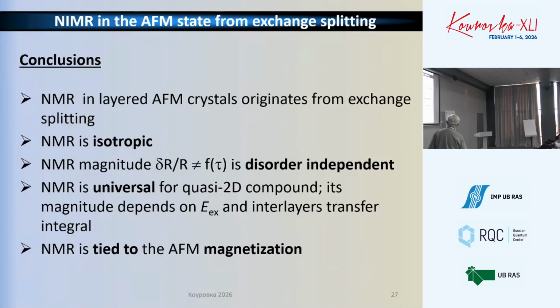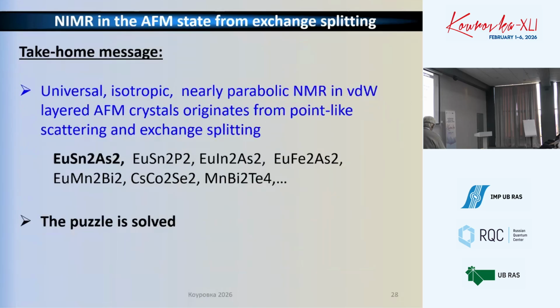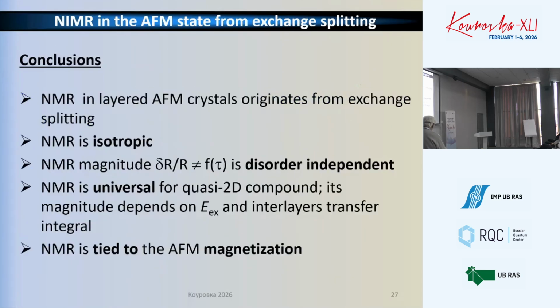I wish to make a conclusion in this section. The negative magnetic resistance in antiferromagnetic crystals originates from exchange splitting. It's isotropic. Its magnitude is disorder independent. It's universal for quasi-2D compounds. Its magnitude depends on the exchange splitting and the interlayer transfer integral. And of course, this magnetic resistance is tightly related to the antiferromagnetic magnetization. As soon as you fully magnetize the europium spins, the magnetic resistance vanishes to 0.